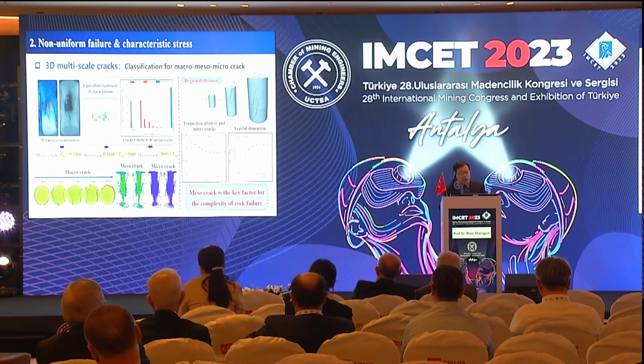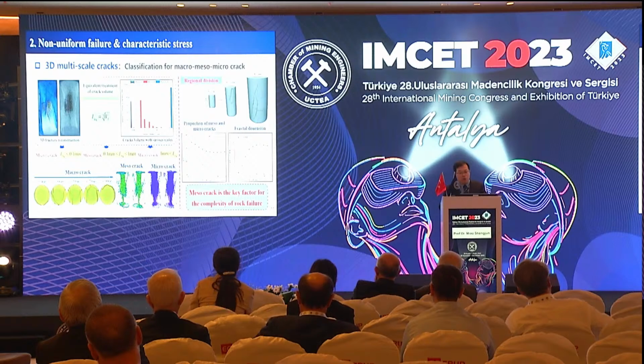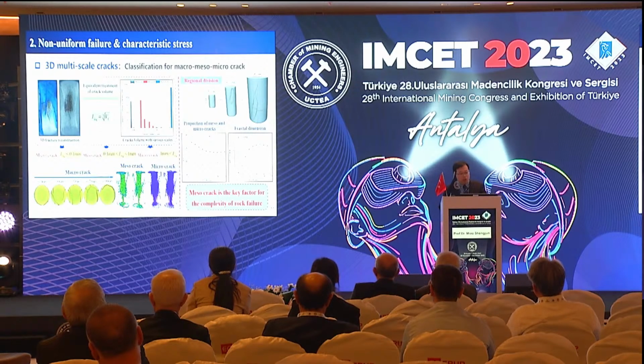Then we analyzed the spatial characteristics in siltstone using CT scanning and three-dimensional fracture reconstruction techniques. By calculating the three-dimensional cracks equivalent volume in the failed specimen, we proposed the volume proportions and fractal dimension of these three types of cracks in different regions. We found that medium-scale cracks were the most critical factor influencing the complexity of rock failure mode.